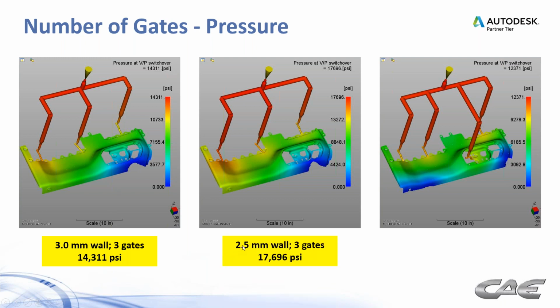When we reduce that to a 2.5 millimeter wall and use the same gating option, now our pressures increase up to 17,000. And if we were to push that even further, now you're starting to get up close to the capabilities of the machine. 20 to 25,000 psi is pretty typical for an injection molding machine. Okay. But this is one of those cases where, that should say 2.5 millimeter wall, with 4 gates, we were able to get it down to 12,000 psi.